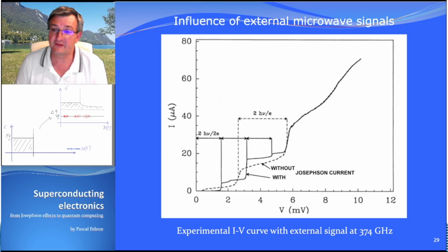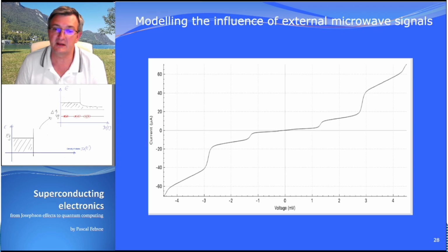Josephson currents, you don't suppress the Josephson current, and you apply a signal at 374 gigahertz, you can see how the IV curve, a measured one, can be very complicated. Because the gap is about here. Without Josephson current, you see this curve here, which is a measured one, right? It goes here, which looks like this one. It corresponds to simulations, basically.